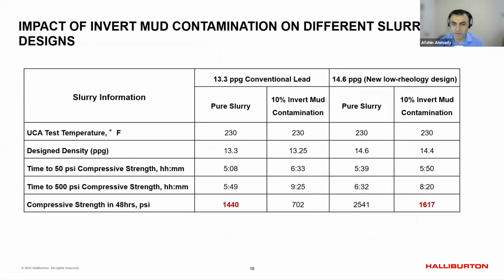One thing I mentioned about the density, why ideally we don't want to reduce the density, it is more sensitive to mud contamination. And here is just some proof. At 13.3 with 10% mud contamination, you see that the compressive strength, especially here, is changing to 702, almost half. And the original compressive strength in 48 hours is 1440. But if you change it to heavier density, it just in theory makes sense. We wanted to just prove it on the actual testing data.